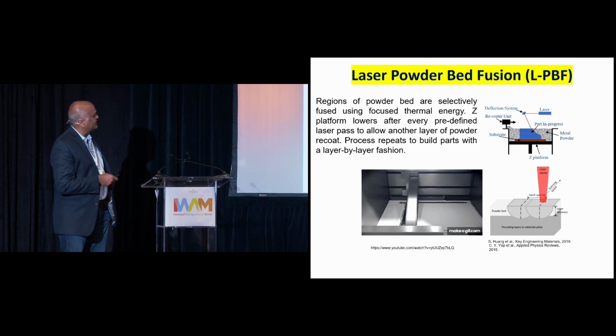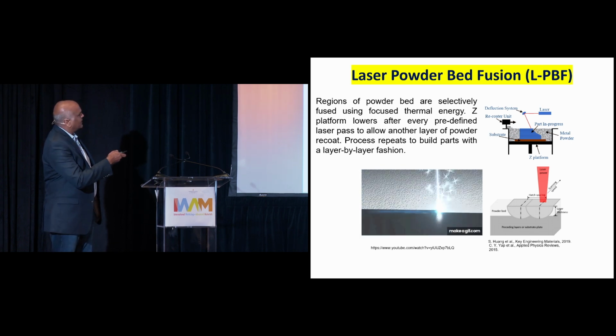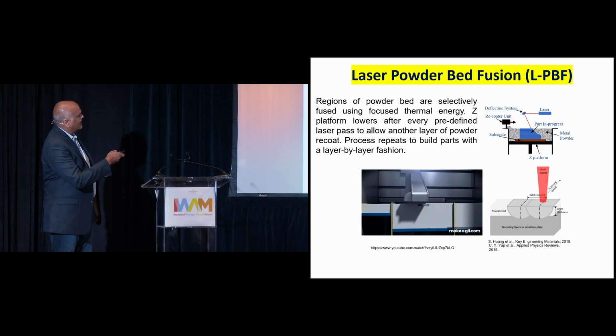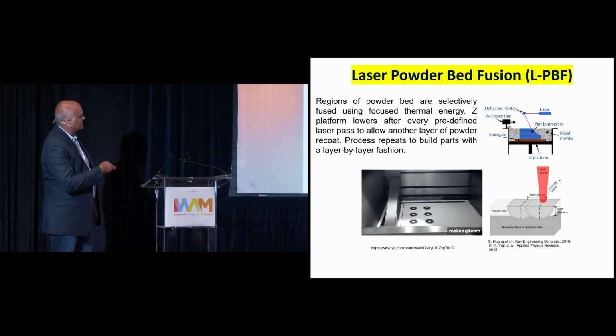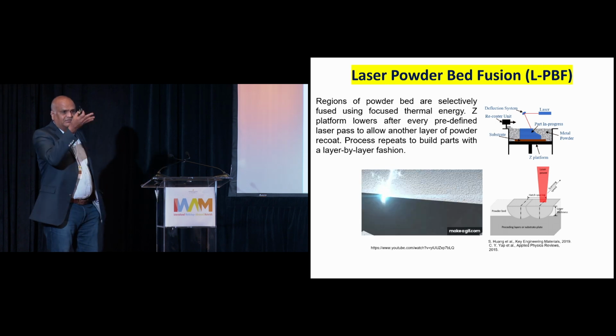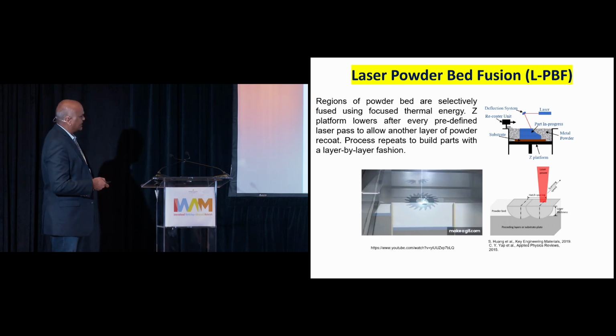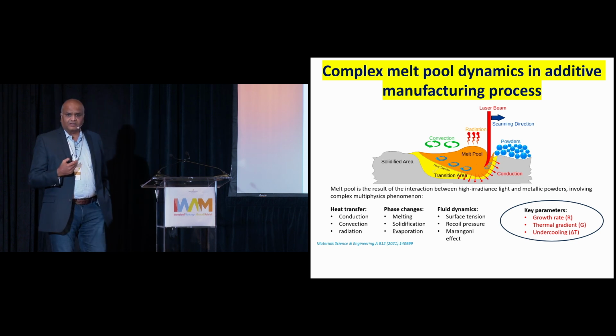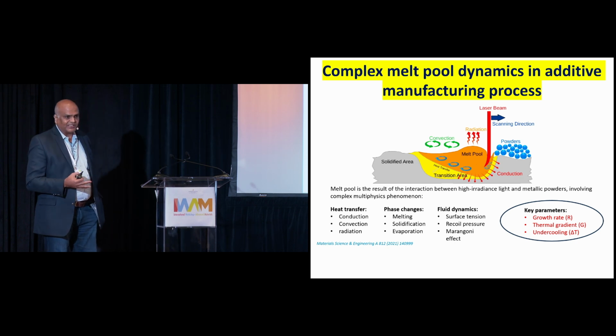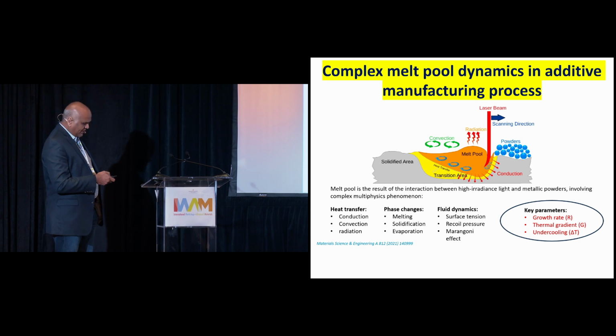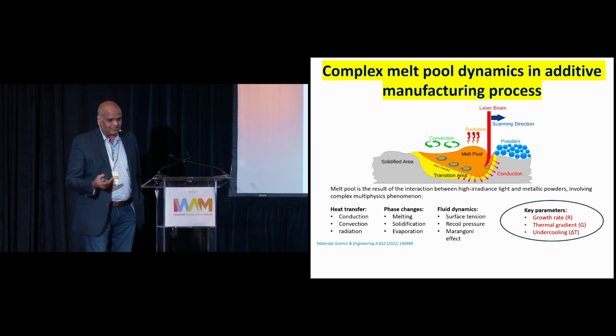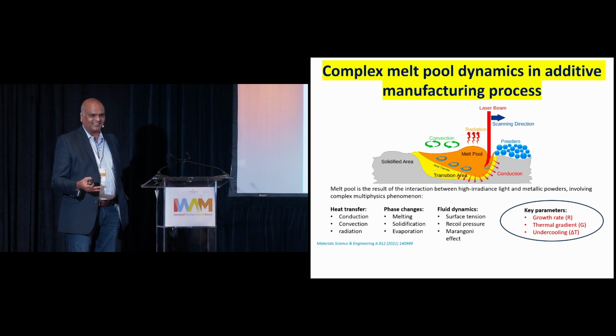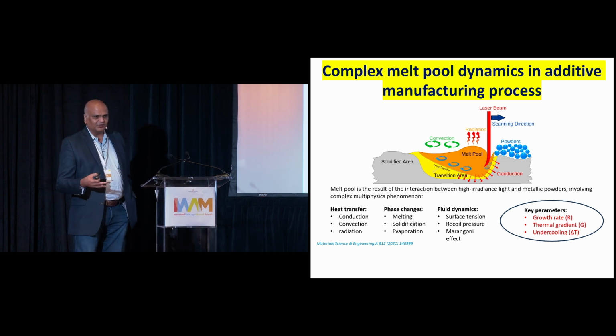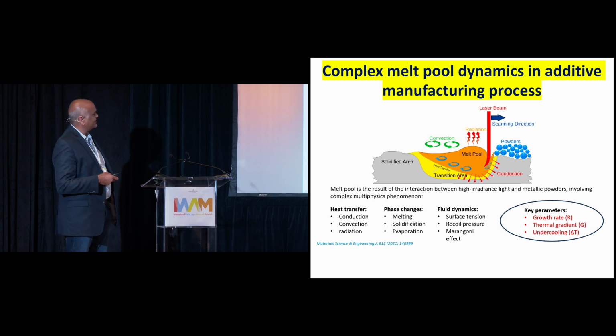Here it is very quickly. What you do is basically spread a layer of powder, then shine a laser on it to melt wherever your specific locations you want, and you keep building from bottom up to get the 3D product you want. The physics of this problem is quite complex. You have all 3 heat transfer mechanisms that are operational here, and you have phase changes, not like my previous speaker talked about from amorphous to crystalline, but melting to solidification, and there is also some evaporation possible.